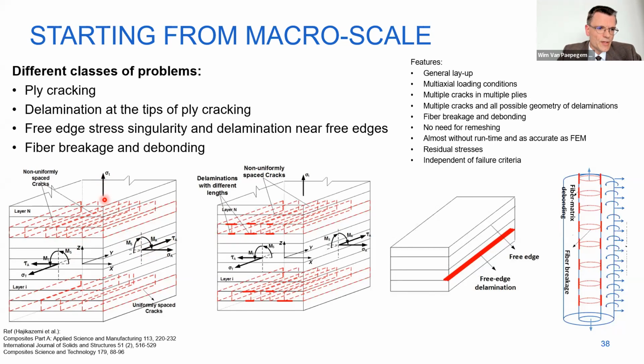And now we want to solve this without finite elements. You could argue, yeah, this is practically impossible. Well, it is indeed not easy. I mean, you get complicated equations, but to give you a hint how it works, you start with your solution from classical laminate plate theory, as if the material was undamaged. And then every crack is, put a bit simplified, like a stress boundary condition. So we assume the crack faces are open, and then it means that on the crack faces, the normal and shear traction stresses are zero. This is an additional boundary condition for your problem. If we do this for all of them and we properly separate the domains, you can solve this and have access not only to the global behavior, but also to the local behavior. So we also have the local stresses.